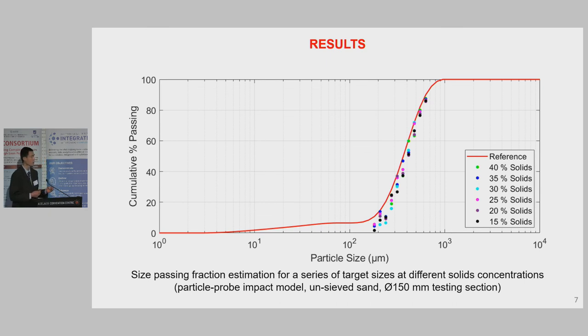The scattered dots are the estimation results for the size passing fraction for a series of target particle sizes. As can be seen, there is no apparent difference among the results under different solid concentrations. That shows good robustness of our sensor, which is not affected by the different solid concentrations. But we do see some error when the particle size starts to decrease. That's the limitation of the particle probe impact model, and that brings the necessity of using a flow-induced drag model.